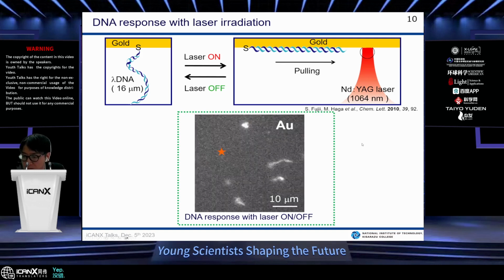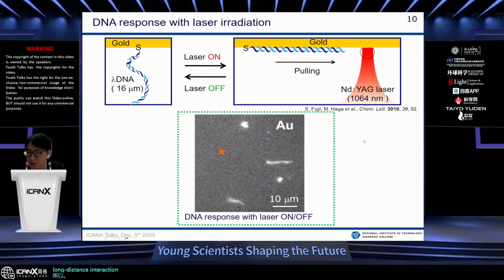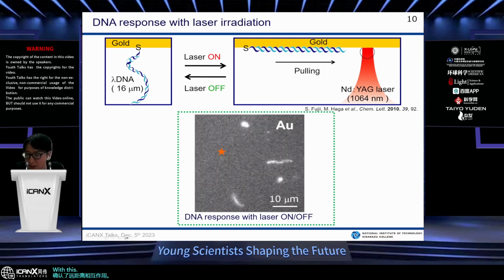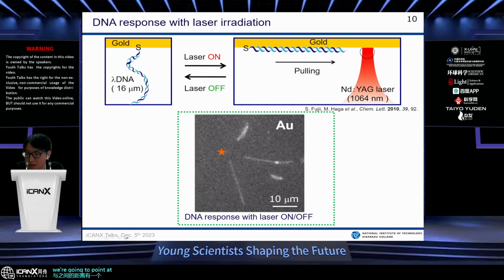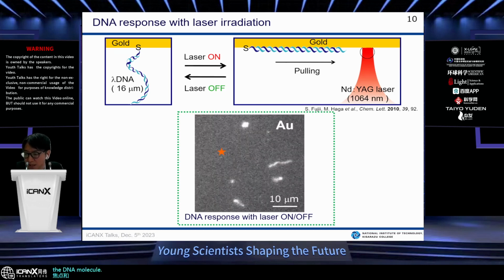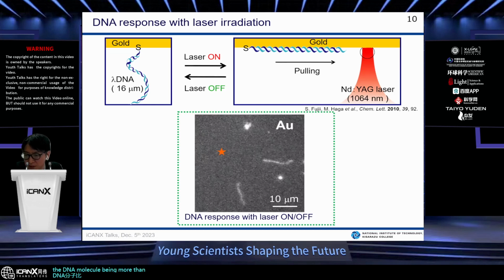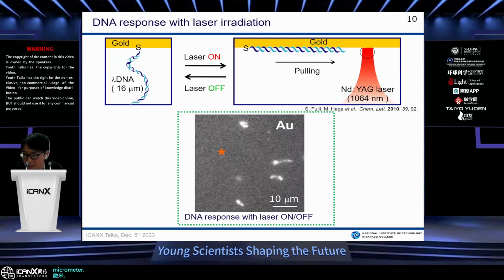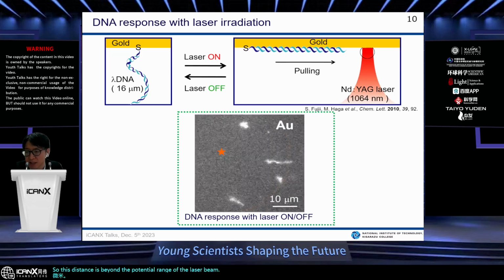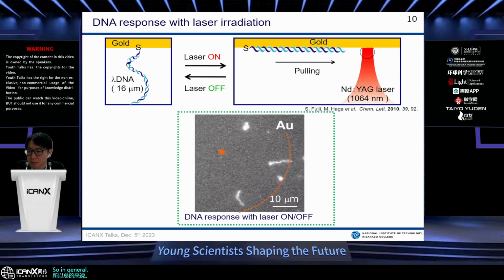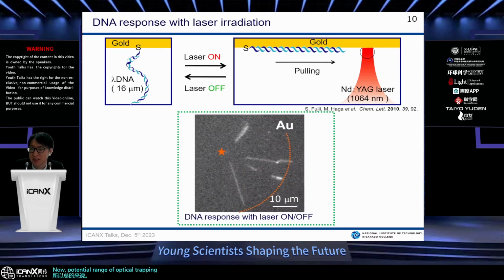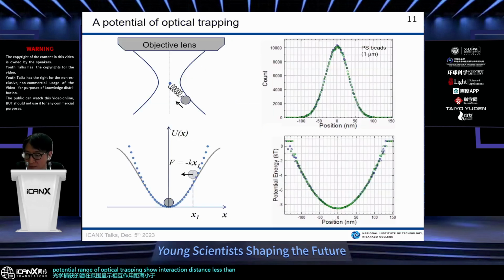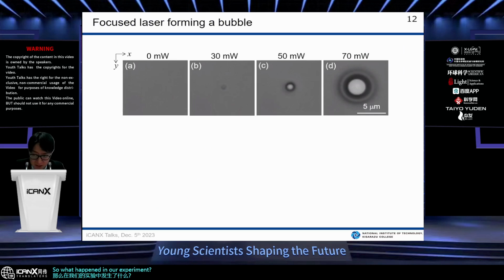Here. So long distance interaction was confirmed, with the distance between the laser focal point and the DNA molecule being more than 20 micrometers. So this distance is beyond the potential range of laser trapping. In general, the potential range of optical trapping shows an interaction distance of less than 1 micrometer. So what happened in our experiment? The answer is microbubble generated by laser local heating.